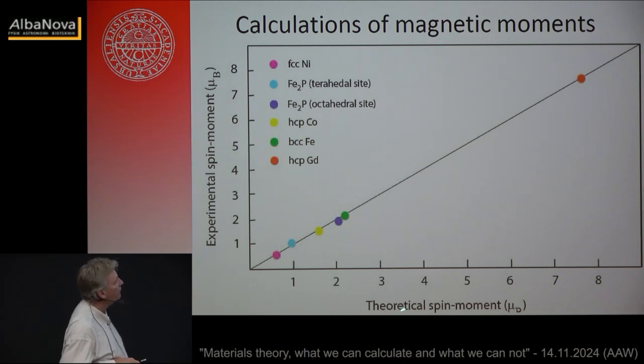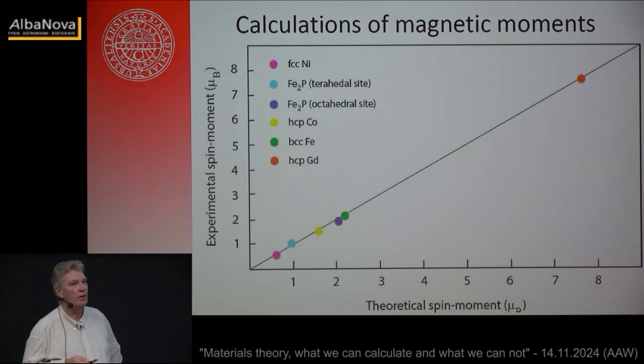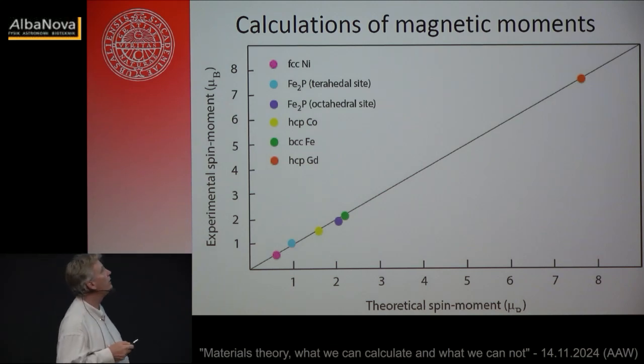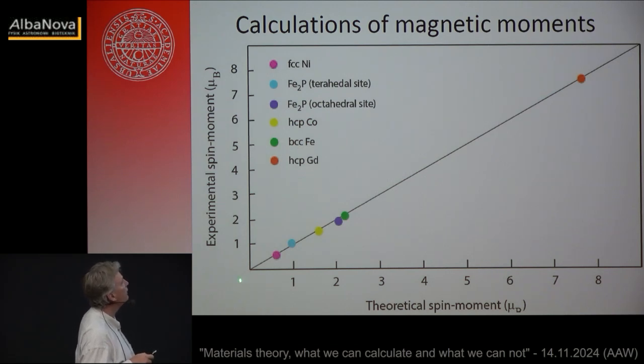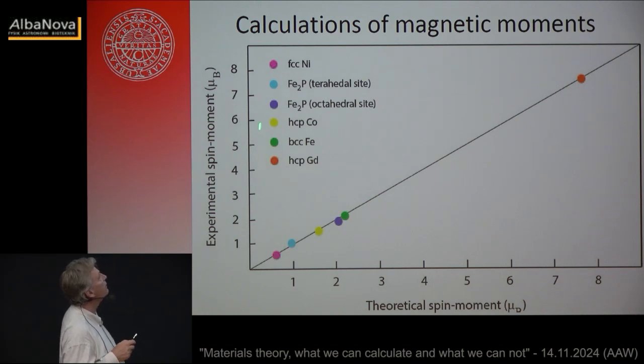Here you have the theoretically calculated, the DFT calculated spin moments, and here are experimental spin moments deduced from neutron scattering experiments or XMCD experiments or magnetometry, SQUID magnetometry. There's many tools with which one can do that. And so if the agreement between experiment and theory was perfect, they would all lie on a straight line, this line here. And you can see that this is now a carefully selected group of elements because they're all found to lie on this line. So here the agreement is very good.